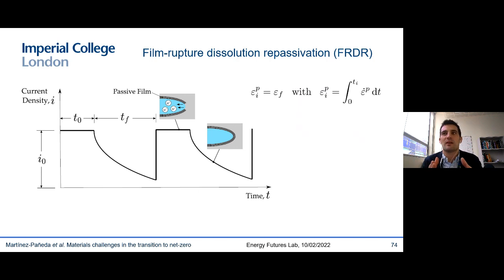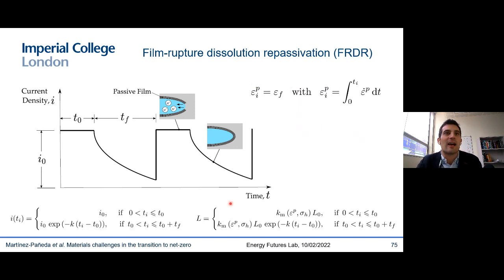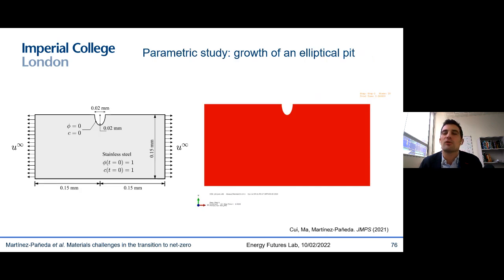What typically happens is that a passivation film is created that protects the metal from corroding, and this lowers the corrosion current density. However, at some point our strains are large enough, and then the film ruptures again, and corrosion is enhanced until the repassivation process begins. So it's a cyclic competition between straining kinetics and repassivation kinetics. And we capture this by means of two features. First, that we have a critical failure strain for the film within each cycle. And second, by enhancing, again, the mobility coefficient through a new parameter K, which governs the stability of the film for that particular environment. So let me show you finally what the model predicts with these enhancements.